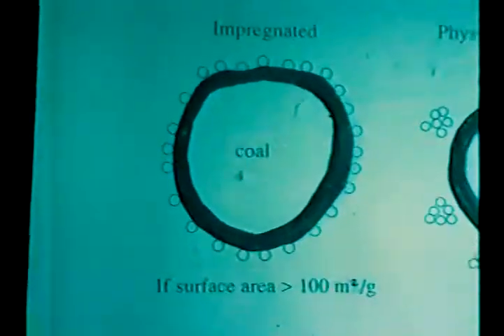And Gibbons found this method is better. Why? He says because in this method, the catalyst is in intimate contact with the coal and maintains a fine particle size upon conversion to the active sulfide phase. So what Gibbons says is this model. He says, in fact, he used this method.